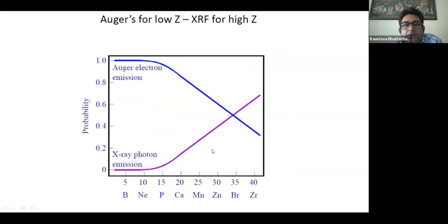Similarly, as I have said, for the Auger, the competitive process will always be an Auger emission or an X-ray photon emission. So there is this comparative probability of XRF, that is X-ray fluorescence, where it emits and fluoresces. For the higher elements, the X-ray fluorescence is more, and for the low Z elements, the Auger electron emission is more. And there's a crossover around the atomic number of 35.